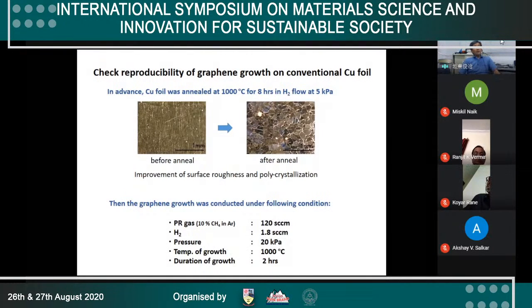Normally most scientists do the annealing in hydrogen flow. So when we anneal the copper foil in hydrogen flow at around 1000 C, the result is like this. After annealing we get a well-defined, well-flattened surface, but of course a lot of domains appear. There is improvement of the surface roughness and polycrystallization after annealing. Then the graphene growth was conducted under the following conditions, and the result is next.